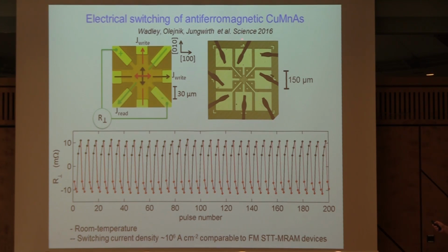And this was done on this type of device geometry, so optical photograph microscopy. And we're switching currents that are comparable to ferromagnetic STT-MRAM devices currently used, all done at room temperature.